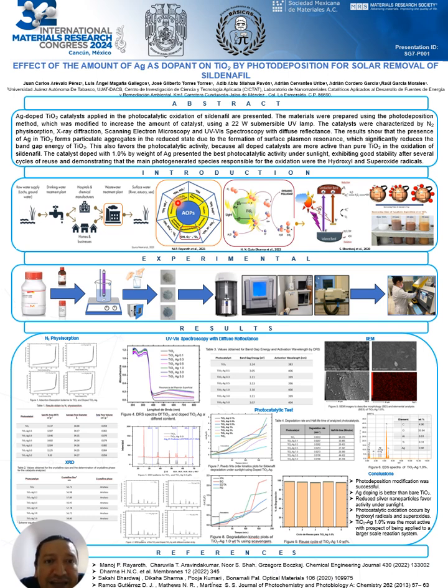It's known that metallic silver nanoparticles as dopant form surface plasmon resonance, which also helps to improve photocatalytic oxidation by forming a Schottky barrier between the interface of the titanium dioxide and silver nanoparticles that also increases the separation between electrons and holes.